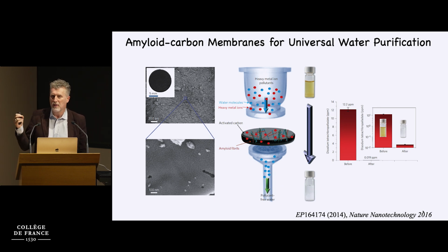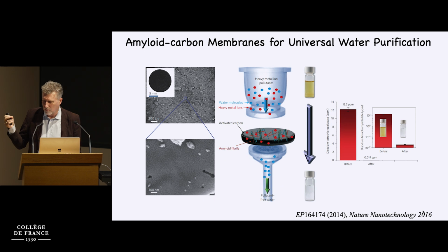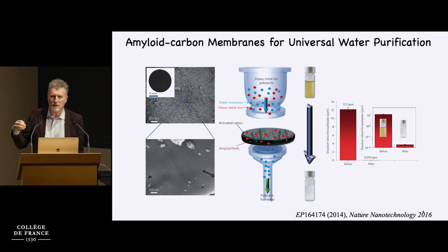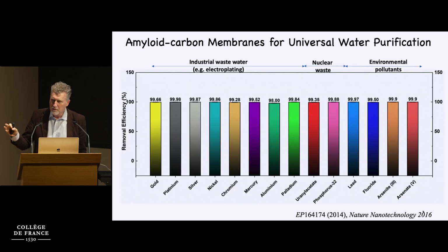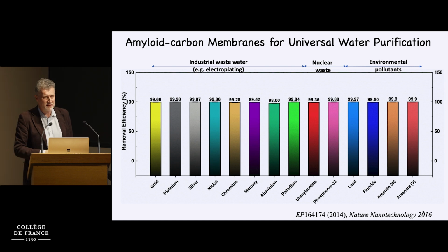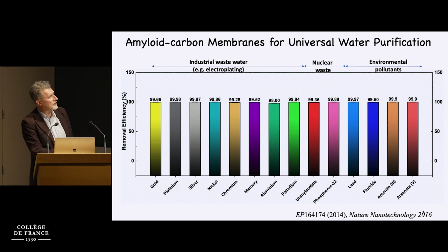So there is nothing magic with palladium. The thing is, if you think about water purification, it's like having 20 ion exchange resins working at the same time. We have 20 amino acids, so whatever the ion you're trying to capture is, you always find the right amino acid, which has a very high binding constant. These are some of the ions that we have removed.